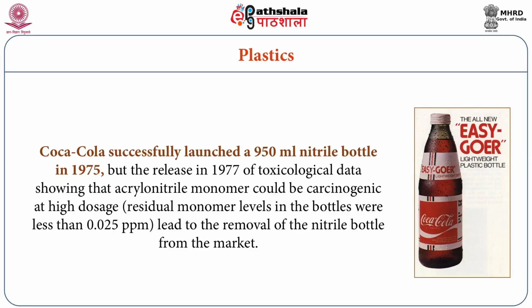Plastic bottles. Coca-Cola launched a 950 ml nitrile bottle way back in 1975, but the release of toxicological data in 1977 showing that acrylonitrile monomer could be carcinogenic at a high dosage, and the residual monomer levels in the bottles being less than 0.025 ppm, led to the removal of the nitrile bottle from the market.